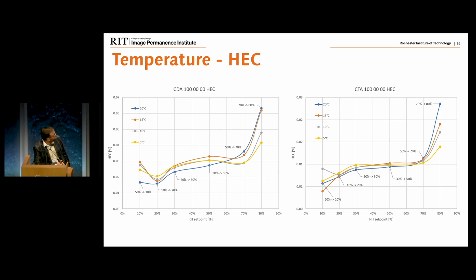So I'm, for example, not wedded to this data at the very beginning. That's why I normalize everything to the 10%, because I'm much more confident. So there is definitely response, especially in CDA. You absolutely see that. What are the amounts? I have not calculated. With the mechanical response, probably the same, especially in the higher humidity when you start seeing plasticization effects of the moisture present. Definitely yes, but again that will require more calculations.